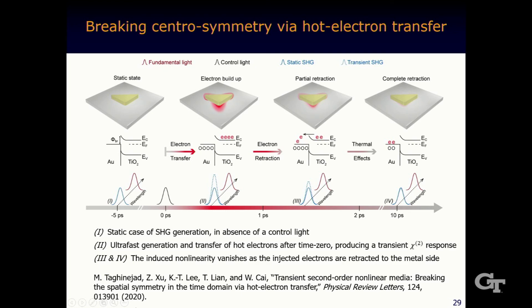More details are described in this paper. You can see that we have a plasmonic structure, and this white substrate-like thing is a titanium oxide, which is amorphous with a zero chi-2. But when plasmonic resonance occurs, the asymmetric physical profile of this plasmonic particle will give rise to hot electron injection, roughly following this profile, and the electrons now enter the titanium oxide. So within a very short time window, we convert this amorphous titanium oxide layer, initially with zero chi-2, into an effective chi-2 material that enlarges the frequency-doubled output from this structure.